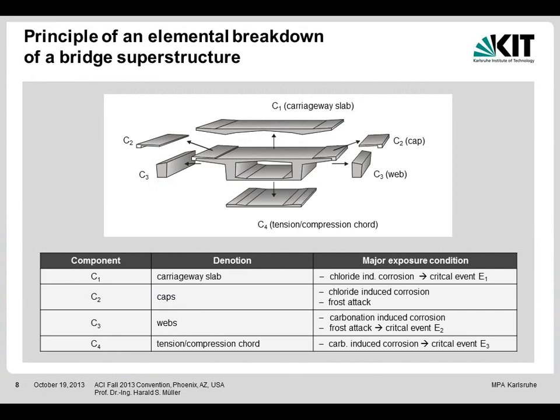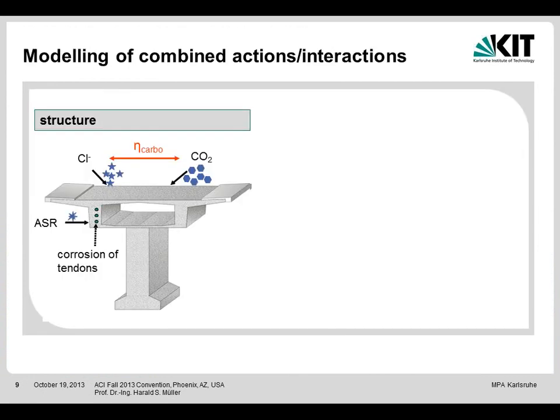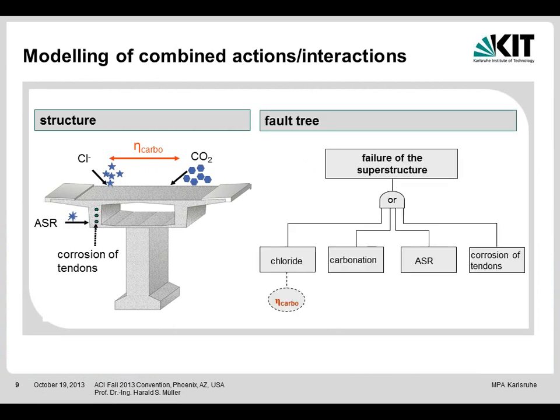And so you go through and define an easy procedure: the major exposure conditions and the critical events. And then you have to bring those things together in a type of fault tree for the superstructure. Very easily done here: if you have chloride-induced corrosion or carbonation, or for example also alkali reaction or corrosion of tendons, all those may lead to a complete failure.